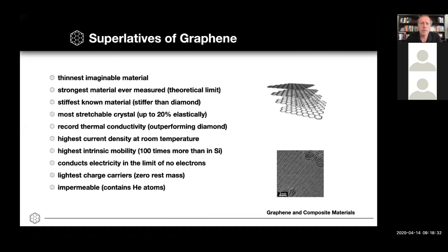In most cases, when you're adding some kind of additive to achieve an improvement in one performance factor, you have a trade-off and you have to sacrifice something. And many times with graphene, that's not the case. For example, in elastomers and rubber, the trade-off is typically, if you want more traction, you have greater wear, it becomes a softer rubber. And if you want to have better wear, you make a harder material that doesn't wear as much, but you lose traction. And we've seen in many applications, whether it be in footwear or in road tires, that graphene has broken that law that you have this trade-off. So you can get both better traction and improved wear at the same time, which is just phenomenal for a material like rubber, which has been around for decades. But that dynamic has always applied.